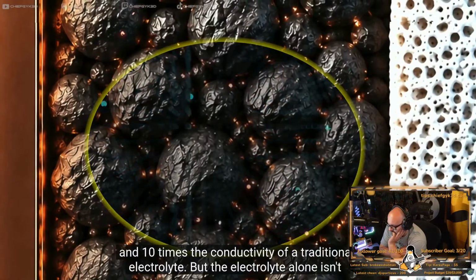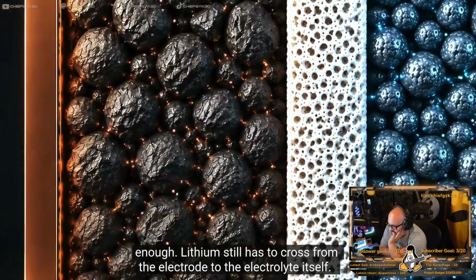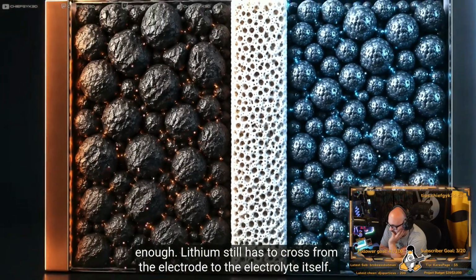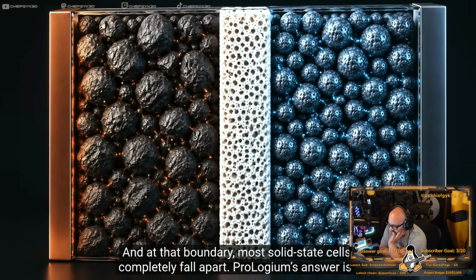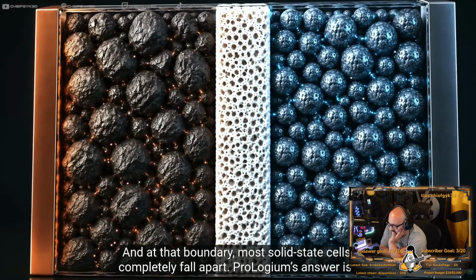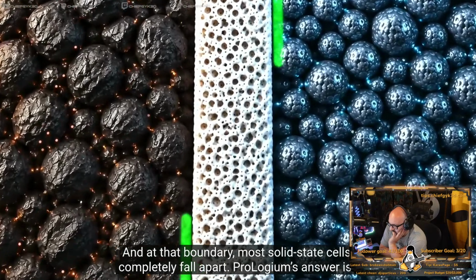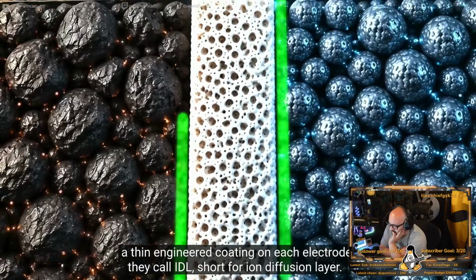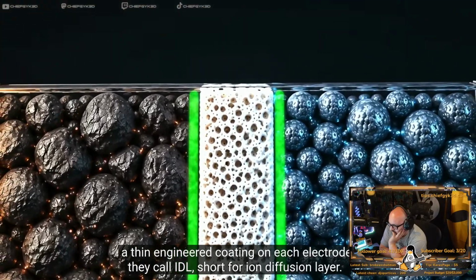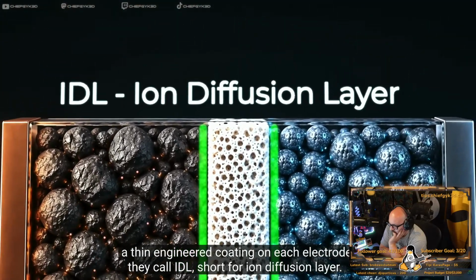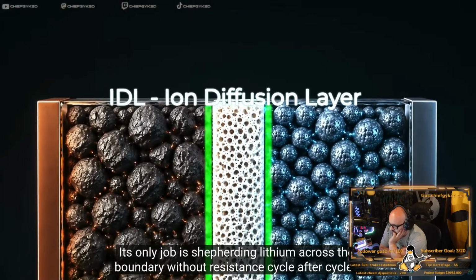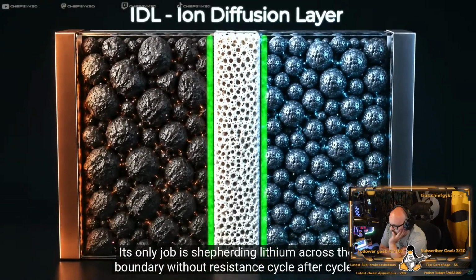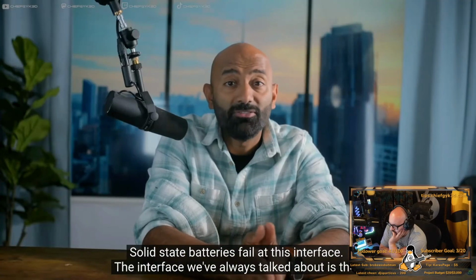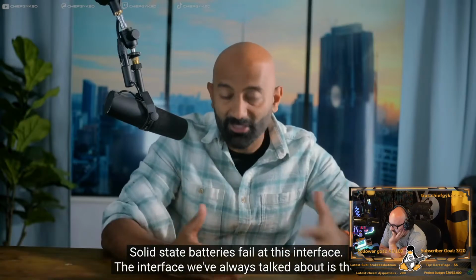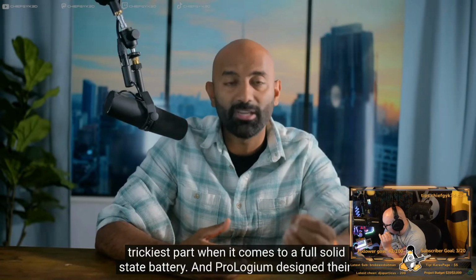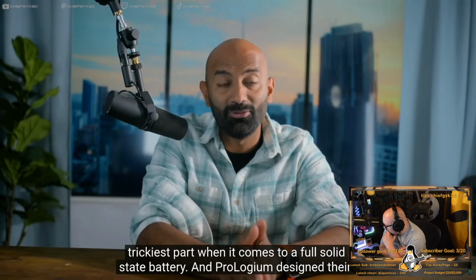But the electrolyte alone isn't enough. Lithium still has to cross from the electrode to the electrolyte itself. And at that boundary, most solid-state cells completely fall apart. Prologium's answer is a thin engineered coating on each electrode they call IDL, short for ion diffusion layer. Its only job is shepherding lithium across the boundary without resistance, cycle after cycle. Solid-state batteries fail at this interface. The interface we've always talked about is the trickiest part when it comes to a full solid-state battery.